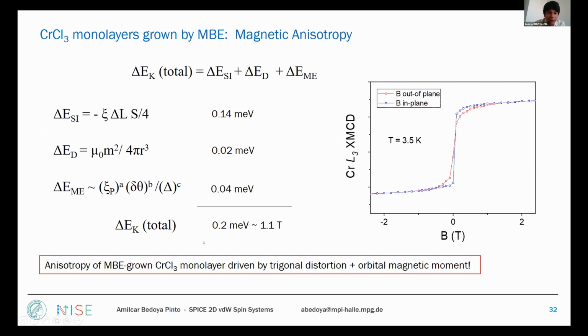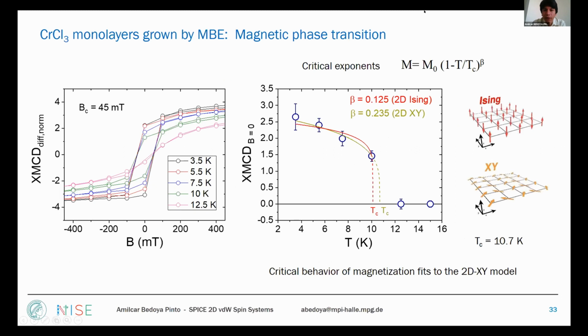And when we put the maths roughly here, we arrive at 1.1 Tesla, which is not so far away from the values that we have observed experimentally. So I think I'm running out of time. Just to give you some idea of what we have done, as I told you, we have also looked at the phase transition, and when we model this